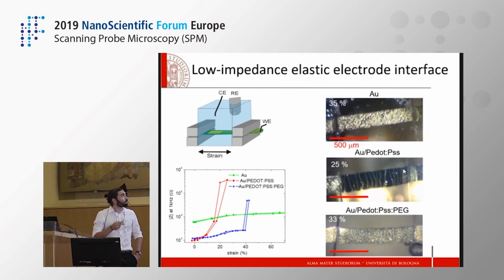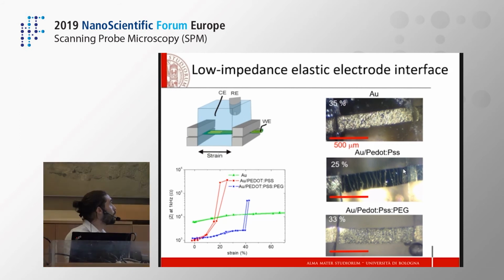The important property of the PEG can be understood when we study the electrochemical impedance of our system under strain. Indeed, for a standard gold electrode, the impedance is more or less constant during the strain up to a value of 60%, because gold basically forms micro-cracked patterns that are still able to conduct between the different gold islands. While when we introduce the PEDOT:PSS, huge cracks start to form and there is a steep increase of the impedance at 10% and we lose the contact at 20% of strain.